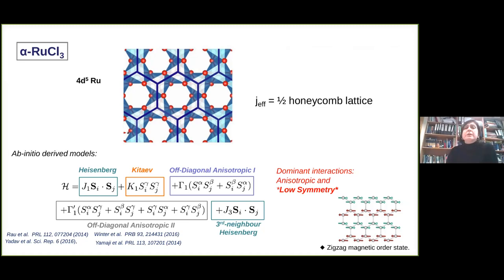However, as we know, materials are not perfect. They have distortions. They have, in fact, many other effects coming into the description of its properties that may induce interactions other than the interaction we want to fulfill. And in fact, we know by now that the magnetic description of this system of alpha-ruthenium trichloride is not only given by a strong Kitaev interaction, but it also has other anisotropic spin interactions that play a role in the description of the properties of the system. One of the important parts of the interaction is what we call the gamma interaction.